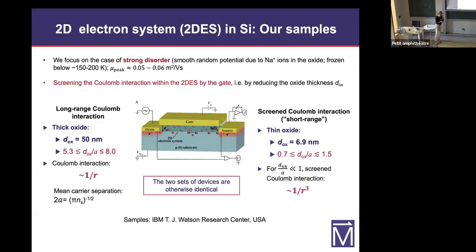So we had two sets of samples, both fabricated simultaneously. All the fabrication steps, and there are more than 100 of them, are identical, except for the thickness of the oxide. These samples had, for MOSFETs, a relatively strong disorder. Again, the only difference is the thickness of the oxide. In one set of devices, the oxide thickness was such that the interaction between electrons in the 2D layer is just 1/r. But in another set of devices, the oxide was closer to the 2D layer, closer than the mean electron separation in the regime of interest.